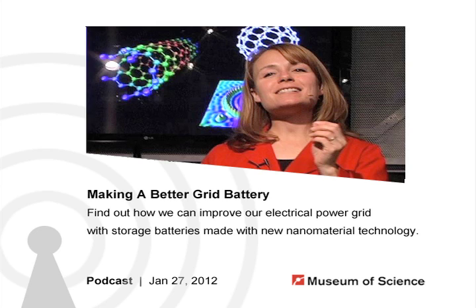So how close are we to actually being able to use some of these batteries in an everyday situation? We're not quite there yet. It's still relatively in the early phase. Cui's team mostly demonstrated that these electrodes work, that we can charge and discharge them 40,000 times without losing capacity. But they're still fine-tuning the chemistry, and they're working on making prototype batteries. They've really just worked out the electrode piece of it. So the next part is they're making these prototype batteries to test out. But at the very fundamental level, they're using cheap and easier to get materials, and they can do the charge-discharge. So now it's just fine-tuning and making it work for a production level.